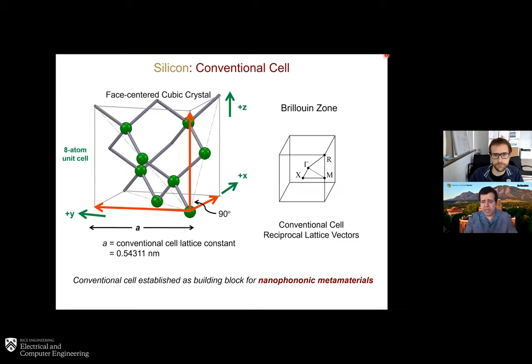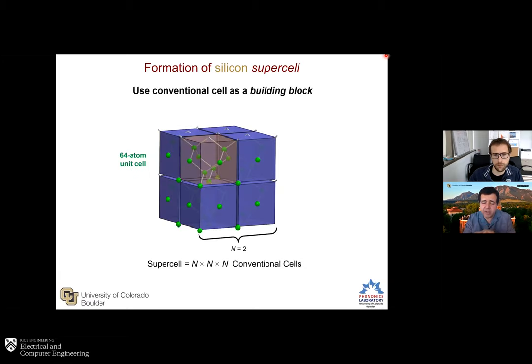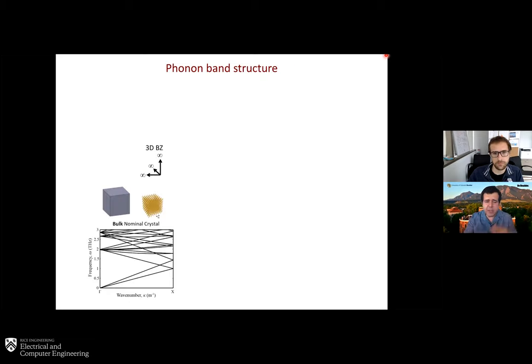So with that in place, we can put those conventional cells together and form a building block. We will, of course, use an appropriate interatomic potential. In this work, we're using the Stillinger-Weber potential. In this case, we have 2 by 2 by 2 conventional cells forming 64 atoms, but we can grow our building block, and then we can explore different configurations. So we'll start with bulk. That building block, we take as is and apply Bloch boundary conditions in all three directions. And that's, in fact, what I've showed you before. And from there, we have a band structure for our model.